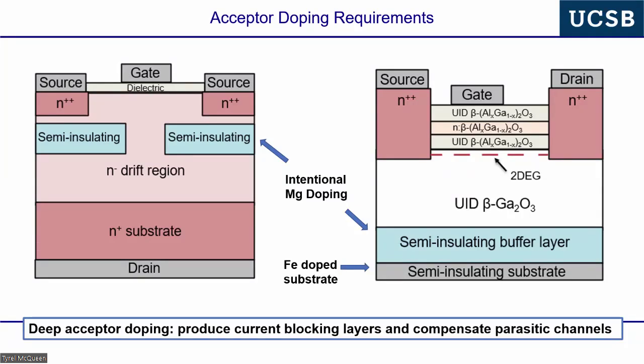So there are lots of reasons in devices to have semi-insulating layers. If you're making lateral devices, like we've worked on a lot, making AlGaN two-dimensional electron gases, you don't want to have any other conductivity. You want to have a semi-insulating substrate. There are a lot of device technologies where we want intentional semi-insulating regions. This is based on something similar to a device my colleague at UCSB, Umesh Mishra, has worked on, a CAVET. This is what a CAVET design would look like, where there are epitaxial semi-insulating layers.